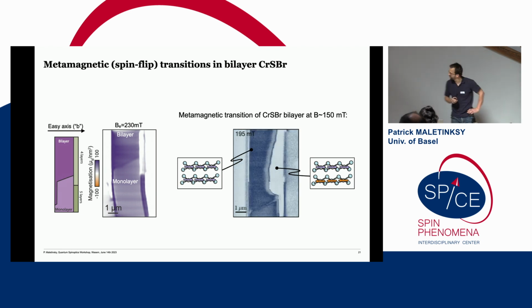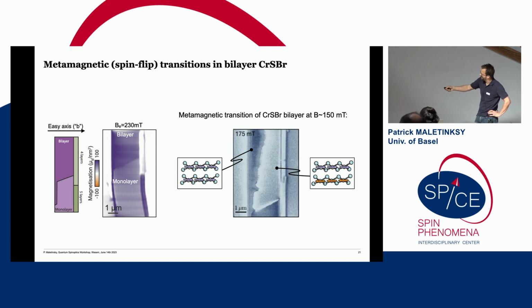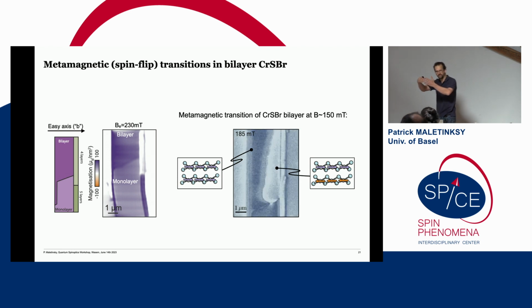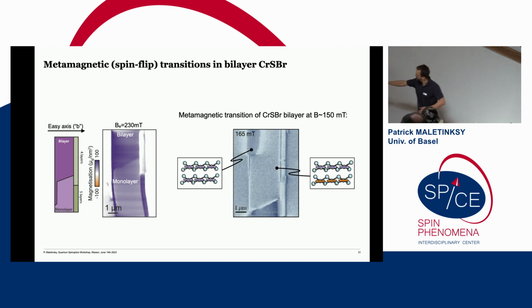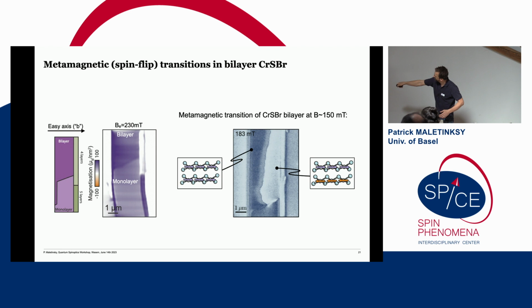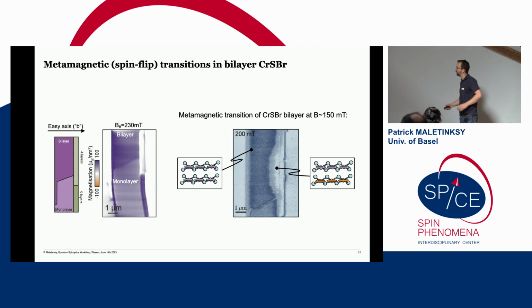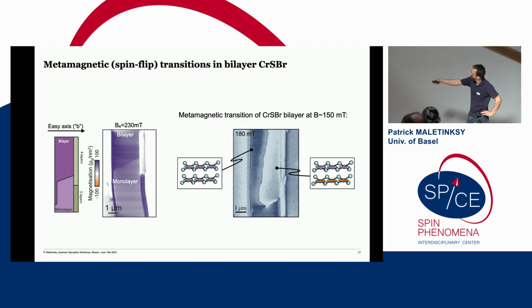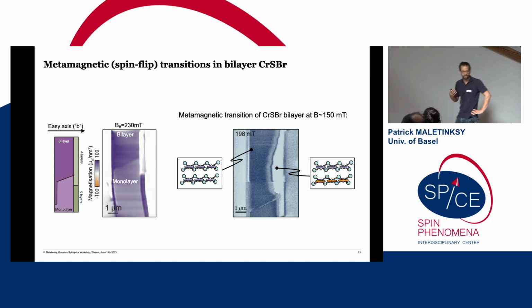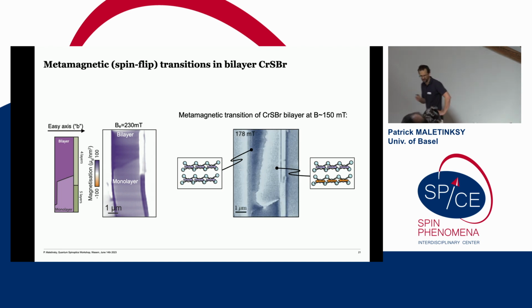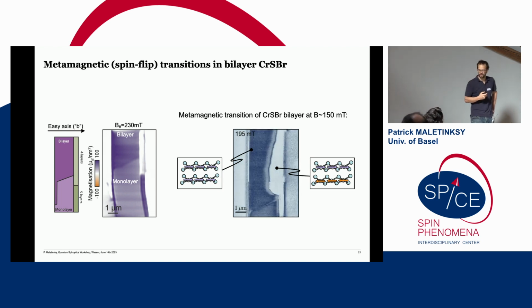I like that movie, first off. We think it does contain some interesting physics. You see how this wall seems to stretch through that material, a bit like a soap bubble that has some boundary conditions and tries to warp around these corners and then collapses very, very quickly. You also see that there is very little roughness, which indicates little pinning and disorder in this material, which is also indicative of the quality of these flakes.